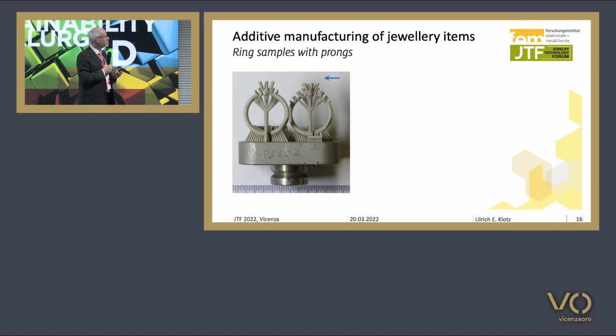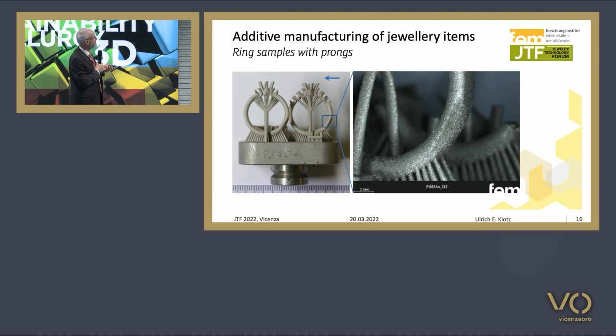If you look carefully, you see that something is wrong here at the right side of the ring, but only on the right side. If you look in detail, we see that the surface is porous here, and some material is missing. And of course, this is a non-acceptable defect.